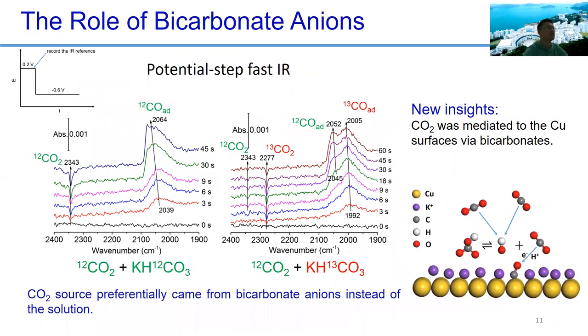We further did a faster scan experiment using a potential step instead of the potential scanning, okay? So from 0.2 volt, there's no CO2 reduction, jump to minus 0.6 volt. So there's CO2 reduction. Okay, so after the first spectrum, you can see 3 seconds in the system of carbon dioxide purged bicarbonate solution, both the carbon are carbon 12. Okay, we see this carbon dioxide reduction because of the consumption of the carbon dioxide. Okay, and the appearance of this carbon monoxide in this position. So that means the carbon dioxide reduction occurs immediately after you reach this negative potential.